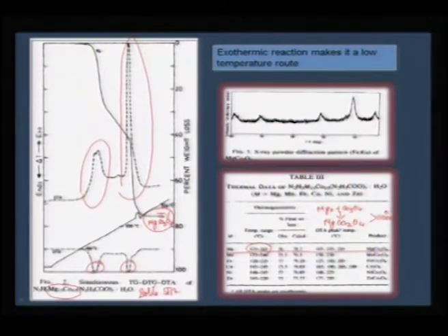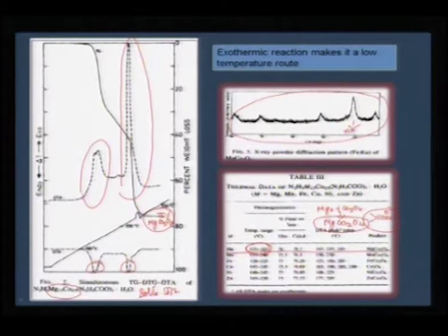You need this much of thermodynamic requirement for this spinel phase to form, whereas in the solid solution precursor route, you are able to prepare the same compound at a low temperature of 265 or 300 maximum, let us say. So, at 300 degrees C, if you can prepare such a spinel compound, then the compound has to be highly reactive, and that is what we see from this X-ray pattern, that the X-ray pattern clearly shows broad peaks indicating that they are nano in size.